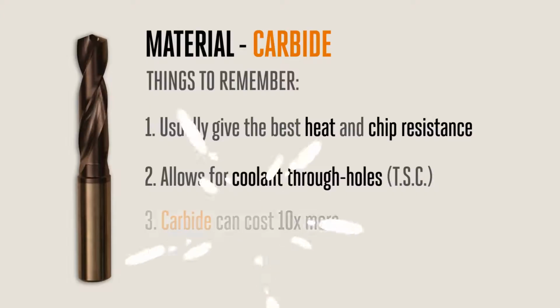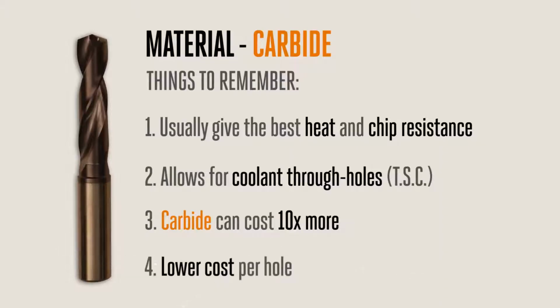All that said, a carbide drill can easily cost 10 times more than a cobalt drill, so the investment is a lot higher. Despite the high price, the cost per hole when using carbide will usually be the lowest, since it can produce so many more holes. Also, because carbide is typically capable of running 3 to 5 times faster, the decreased cycle time to produce those holes goes right to your bottom line.